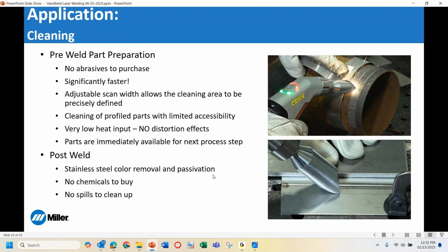Now, when we look at some of the benefits there, there are the ongoing or replacement costs of abrasives. One of the big things is whenever we're using rotating abrasives, the send off or the cast off with potential wires from a bristle brush, that grinding dust that is generated and all the mess that creates. A lot of times you might have joint accessibility issues where getting a 4-inch or a 7-inch angle grinder into a component in order to clean the rust off of it can be cumbersome, or if you have complex profiles, that can become cumbersome for a tack welder or a welder to access. With the laser energy, if you can see it, you can clean it. And so as long as we can satisfy that nozzle safety contact, that allows us to clean the components and strip that rust off.